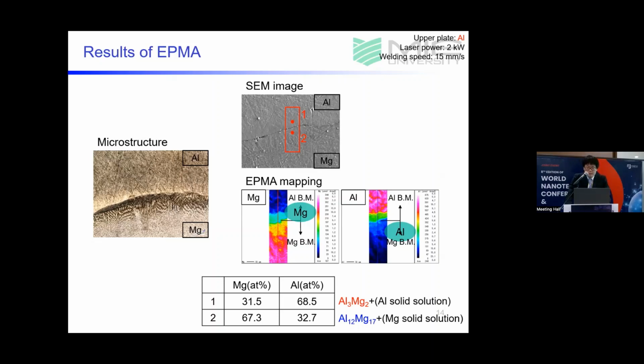From the EPMA results, magnesium was detected on the aluminum base metal side, and aluminum was detected on the magnesium base metal side. In addition, the table at the bottom shows the result of quantitative analysis of the locations indicated by red dots, number 1 and number 2.